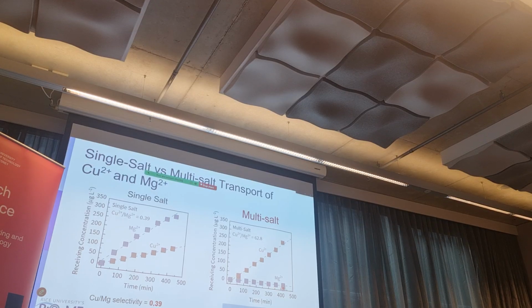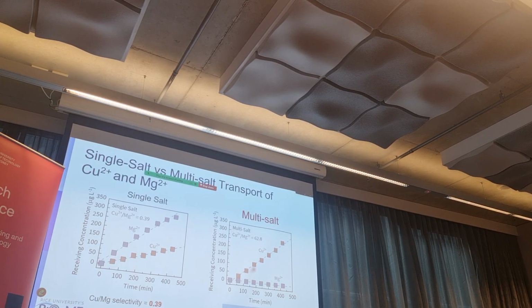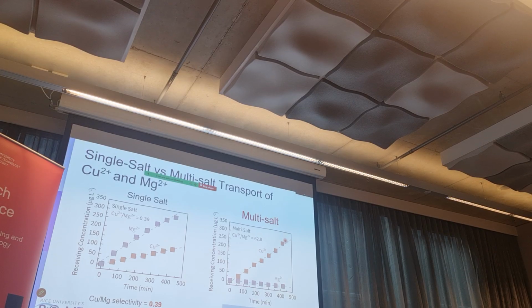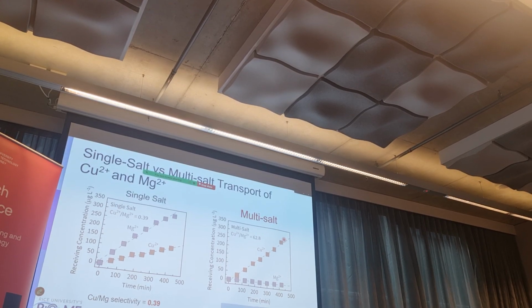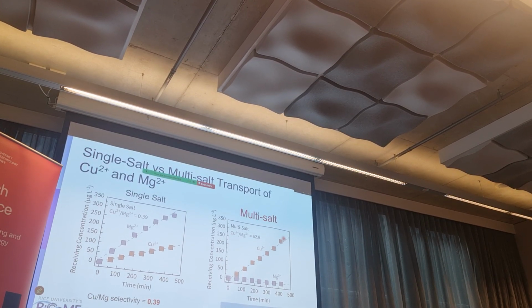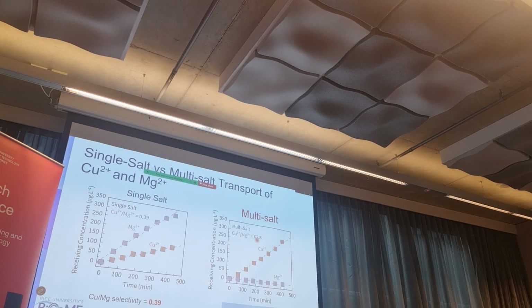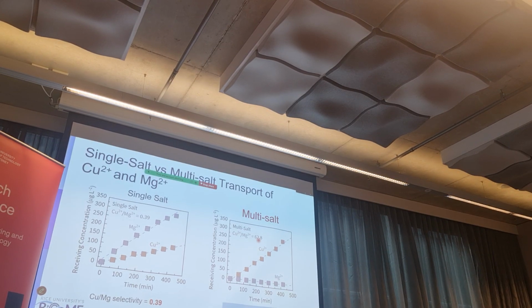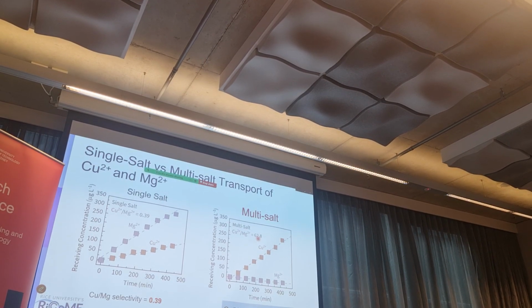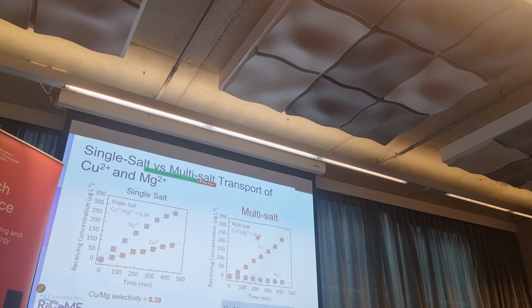Now we can barely measure magnesium flux—it didn't go at all—as opposed to copper, which followed the hypothesized hopping mechanism from site to site. We saw selectivity of over 60. Quite amazing, and we were surprised—or not surprised, whatever.